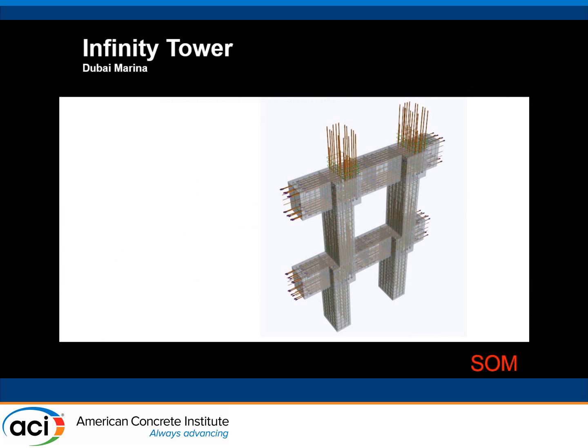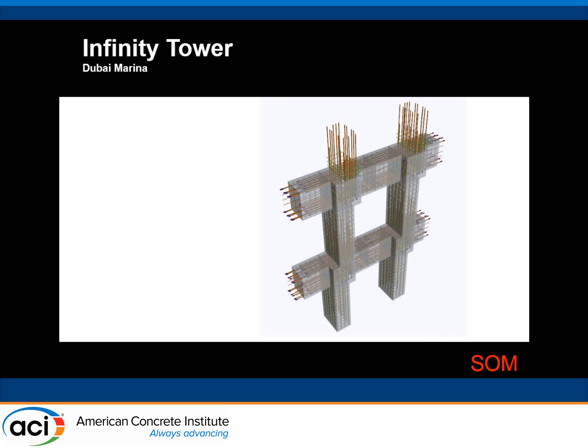Okay, a little bit about the congestion. I talked about the stepped column situation. We knew that there was going to be high reinforcement congestion. It wasn't a surprise. In fact, we did a lot of 3D drawing of these joints and laying out all the rebar so that we could convince ourselves that there was something that's actually constructible and plan how you would do this. And so we drew details of all these joints with the reinforcement in there. We used a lot of rebar terminators instead of hooks. We used a lot of rebar couplers instead of lap splices. Lenton and those people loved us on this project.